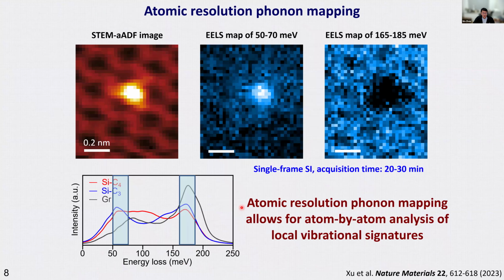So here I just show you that over the past couple of years, we spent a lot of effort trying to improve the stability of our microscope. And this is a spectroscopy mapping taking over 20-30 minutes. And you can see that from a single frame acquisition, we can still have a very good result of the carbon lattice with minimum distortion. So this type of stability will allow us to extract the spectroscopy from each individual carbon atom and to compare their frequency and see how it's affected by the chemical bonding change when we're looking at the defect sites. So this here is the spectroscopy from graphene showing that we have two peaks here corresponding to the